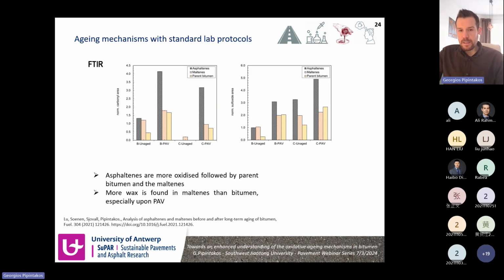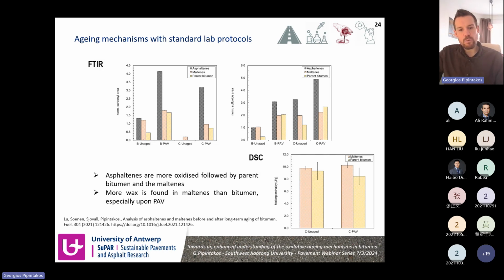Bitumen C was also more complicated because of the waxes, so more advanced analyses were used. First, we separated the bitumen into asphaltenes and maltenes. The results of these publications in Fuel can also be found in the reference at the bottom of this slide. It was shown that the asphaltenes, as studied in FTIR, were more oxidized, followed by the parent bitumen, and the parent bitumen is bitumen C. Also, differential scanning calorimetry showed that the wax was found in the maltenes rather than the asphaltenes, especially after long-term aging. And this has an association with what I mentioned before for the aliphatics that were found via TOF-SIMS.